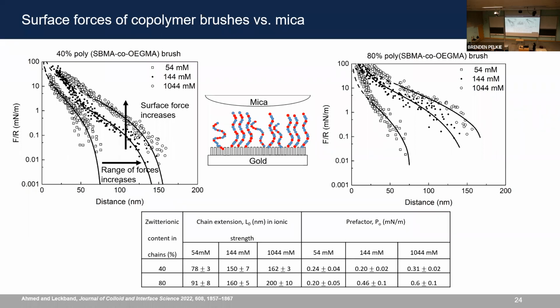And again, for quantitative comparison, we fitted this data with Milner, Witten, and Cates theory, which is more appropriate for high density polymer brushes. And we see that the chain extension, or L0, increases with salt concentration, and we see an increase in chain length only for the 1044 millimolar condition when we increase the sulfobetaine content in the copolymer chain.